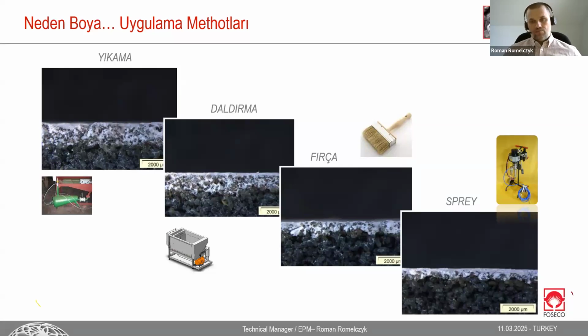When we talk about spraying, it depends on the equipment we have and what kind of coating you use. So the viscosity range is quite big. It's between 14, 18, even 20, and an airless system can be used as well. And what we observe in the pictures is different viscosity, different application methods, and how different the wet layer thickness built on the mold or core is.